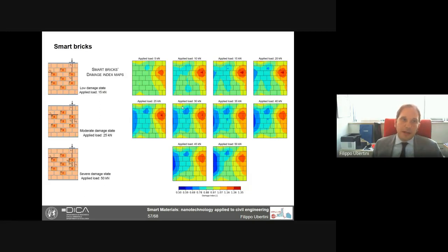If we do this damage location with this damage locating feature, you see that with the smart bricks, we are effectively locating cracks C1 and C2 when they are forming and when they are progressing around 25 kilonewtons. And the only crack we cannot really detect is crack number C3, that is a flexural crack, but this is very unlikely to develop in a real structure.